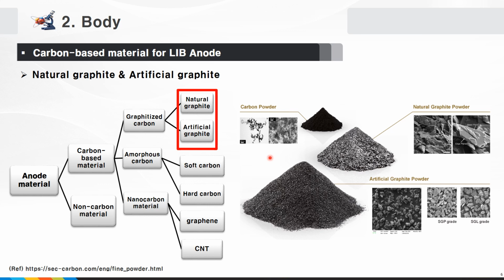Natural graphite has a higher degree of graphitization and is cheaper than artificial graphite, and shows a higher storage capacity for lithium ions. However, because the particle shape has a needle shape or plate shape structure and the edge surface is exposed due to irregular structure, the edge surface is impregnated or destroyed by electrolyte penetration or decomposition when applied to a battery, resulting in a large irreversible reaction. In addition, since the plate-shaped particles are easily oriented on a plane on the current collector, reactivity with electrolyte is not good and electrode density is low.